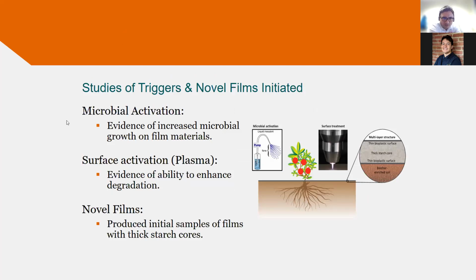In the microbial activation, Harshal is going to present on that. We have some evidence of increased microbial growth on film materials, and there is some interesting stuff happening here. Stay tuned. In the surface activation, we propose the use of plasma, and we have evidence of the ability to enhance biodegradation. And we're also trying to produce novel films. In this case, we see this photo here. We want a thick starch core layer, and then thin polyester layers on top. And Ivan is going to give us some information on that.